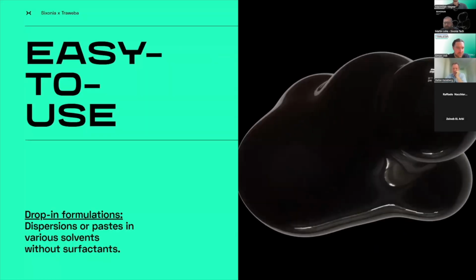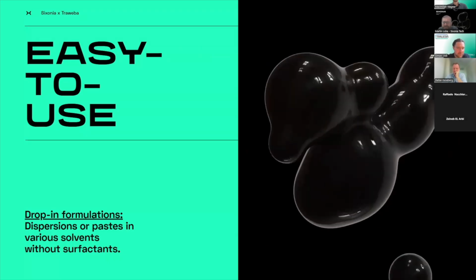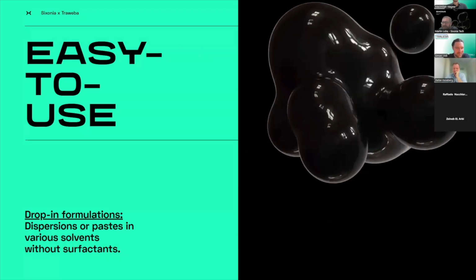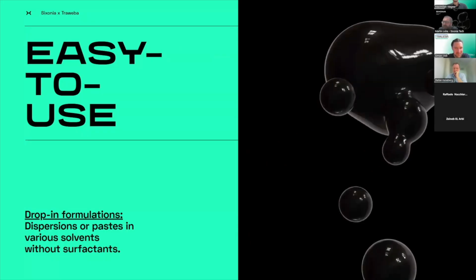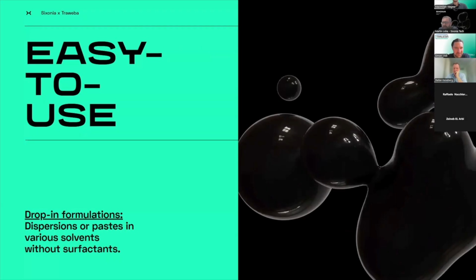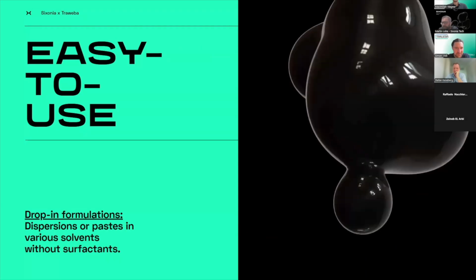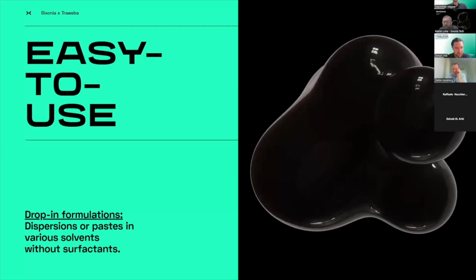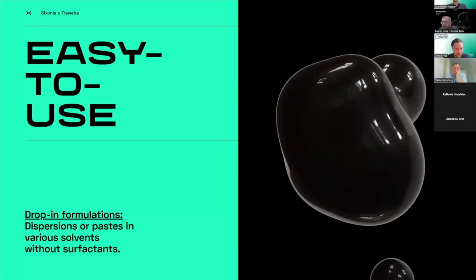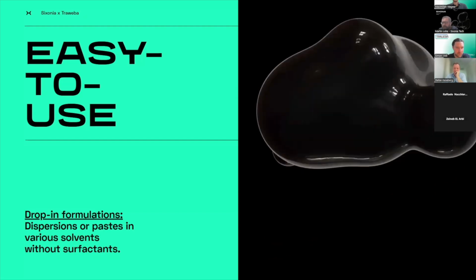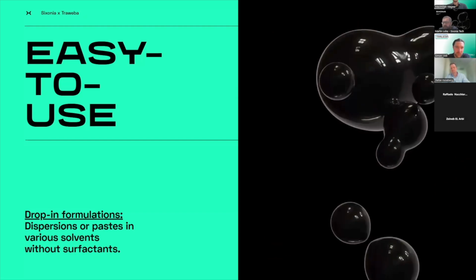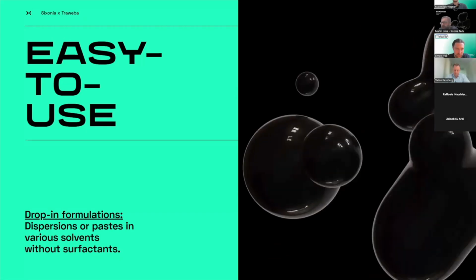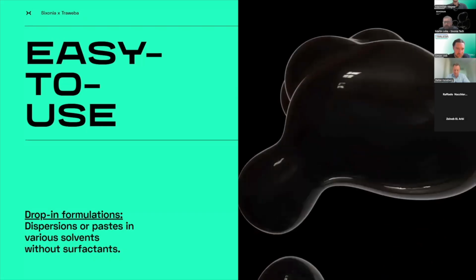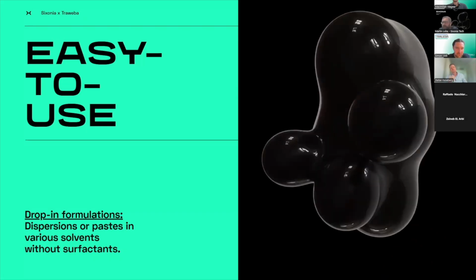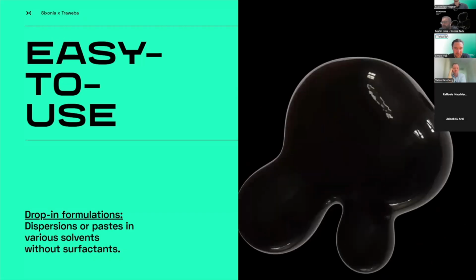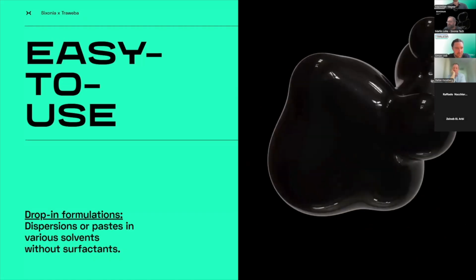It's also easy to use. So what Maximilian said in the beginning was probably true for his research, but it's a pity that you haven't known, or maybe it didn't exist back then. But what we can actually offer is that with our process we can produce graphene that is intrinsically functionalized. So it is easy to process, and we can provide it in drop-in formulations, in dispersion or paste form, in various solvents from water to NMP, or usually whatever the customers require, without any surfactants. So we don't need any binders or surfactants or other additives to stabilize the graphene, and that really makes it very convenient and easy to use.